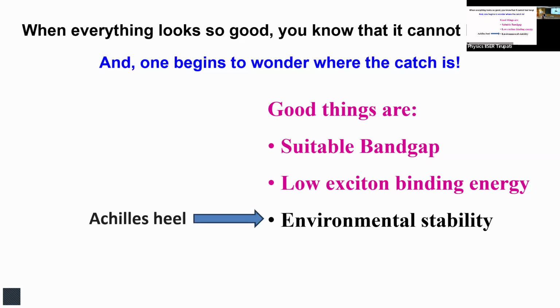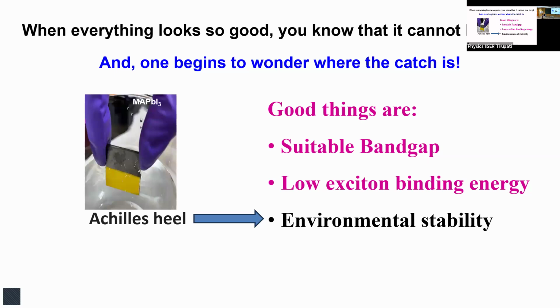What do I mean by environmental stability? This material is fantastic within the first microsecond of its life. After that, I'm exaggerating a little, within an hour or two, it just degrades. You need a solar photovoltaic cell to be alive for 25 years. That's the requirement for commercialization, and this degrades within hours. For example, if you take this device, the material is black in color, coated on a glass slide, and dip it in water, it literally instantaneously turns yellow, which is lead iodide. So the moisture in the environment kills it very, very quickly. This is real trouble, and people are addressing this question.